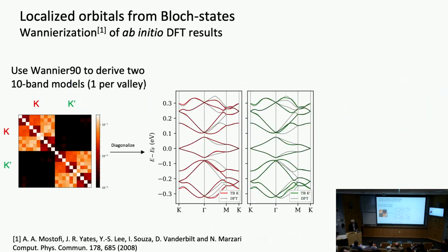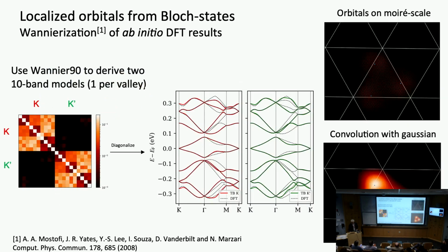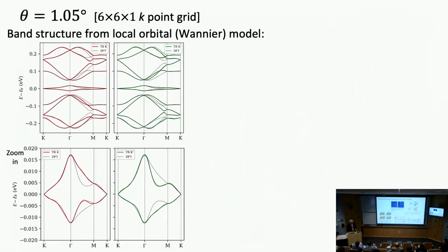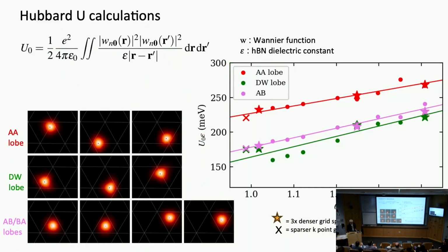So very, very recently, we have been able to break the system down to a few bands. So here are the flat bands. Here are a few bands below and a few bands above, and throw away all the rest. So just keep that as the essential features of the model. This is the kind of wave functions that correspond, localized Wannier functions on the Moiré scale now, that correspond to some of these bands. And with this information, we can do this kind of calculation, for example.